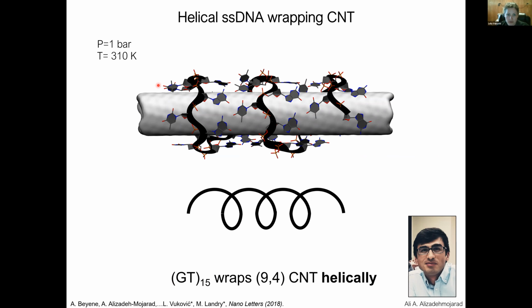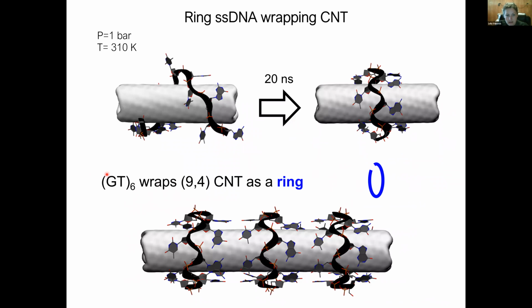When it came to the shorter GT6, we were surprised. It was pretty unexpected for us. We had a nanotube wrapped by GT6, and what happened over time in our trajectories was that GT6 started forming rings on the nanotubes. If you put multiple GT6 polymers, they form 3 rings, as you can see here. They were forming rings very quickly in our simulations, in our snapshots of the system.